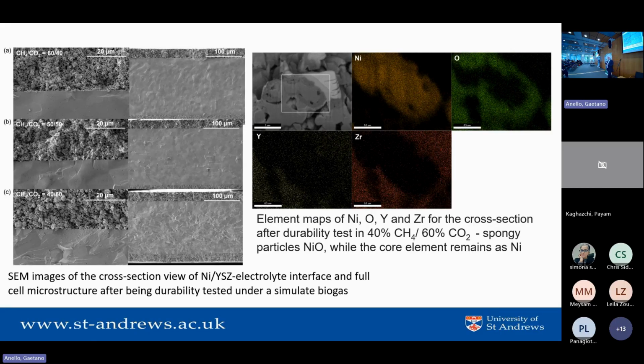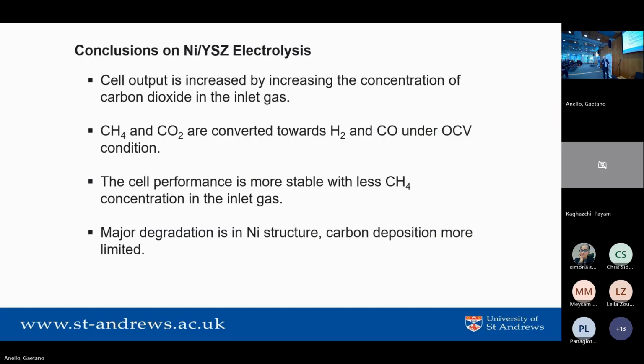So you don't end up with carbon when you analyze it at room temperature, but you do see the electrodes badly degraded. And that's often what you see in these systems. You see nickel migration, nickel reorganization. So it works on the nickel, but you have stability issues.